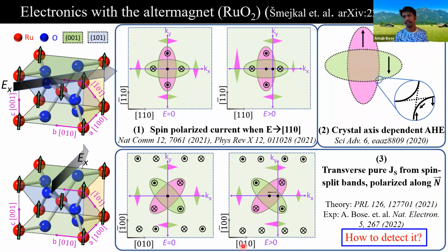But this is fundamentally different than platinum, because for this case, we don't require any spin orbit coupling. The spin split bands are enough, and the spin split is so powerful, so large in this material, that we can have very strong pure transverse spin current, which will strongly depend on the direction of current flow with respect to crystal axis. And the second difference from spin Hall effect is that here the generated spins will be parallel to the Néel's vector. Okay, now the question is, how do we experimentally detect this?